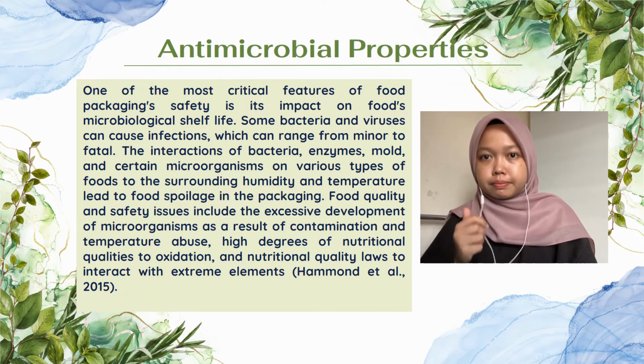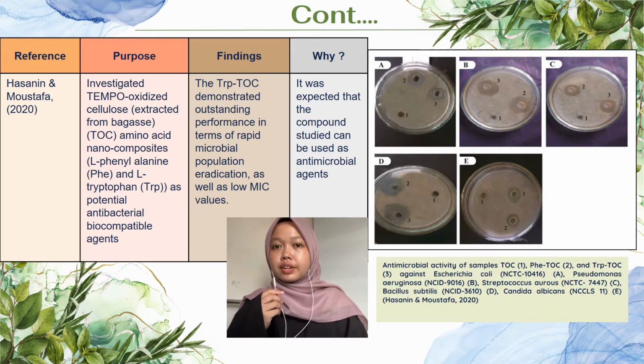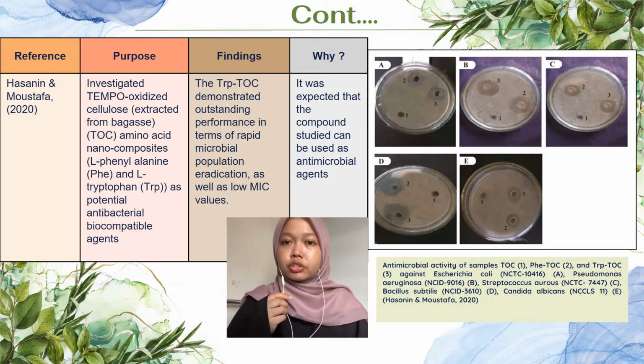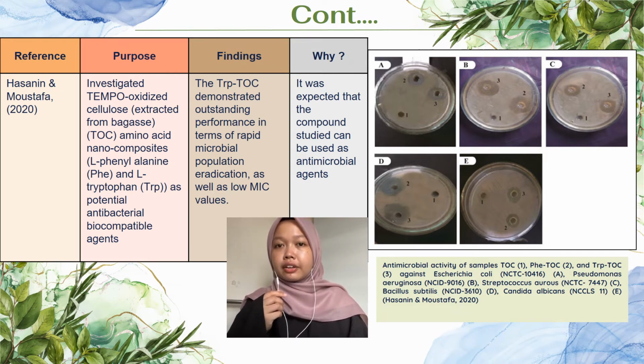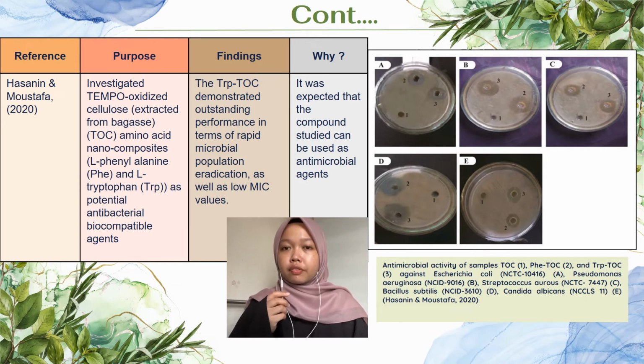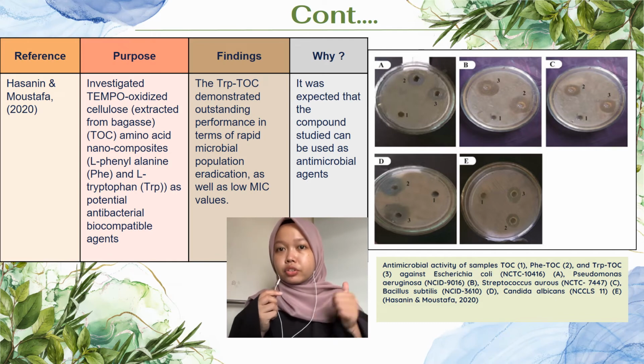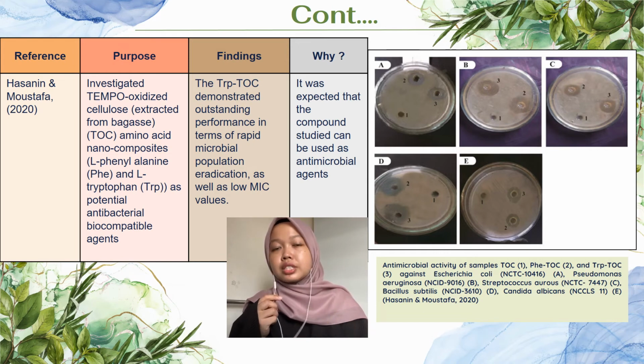microbiological shelf life. Referring to Hassanin and Mustafa, who investigated TEMPO-oxidized cellulose extracted from bagasse as potential antibacterial biocompatible agents, they found out that the TOC demonstrated potent antibacterial action against a diverse microbial population, the majority of which were infectious strains. Furthermore, the TOC demonstrated outstanding performance in terms of rapid microbial killing as well as low MIC values. They used 3 different methods to evaluate antimicrobial activity: agar plate diffusion, statistical analysis of MIC data, and time required for killing. As a result, it was expected that the compound can act as antimicrobial agents.